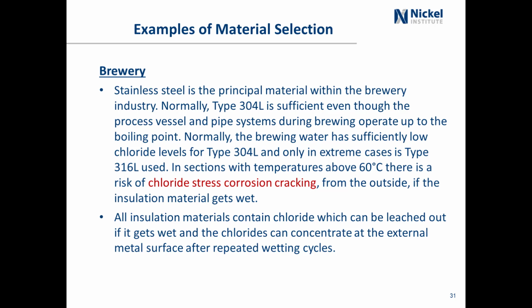But often there are sections that are above 60 degrees C, and there can be a risk of chloride stress corrosion cracking because there can be parts of the brewery equipment that have insulation material on it, and insulation can have chlorides in it. And if the insulation gets wet, the chlorides will leach out and then come up against the stainless steel. And with repeated cycling of wet and dry, the chlorides can concentrate at the metal surface, and then you could get chloride stress corrosion cracking, so you would need a higher grade of stainless steel because of things happening on the outside.